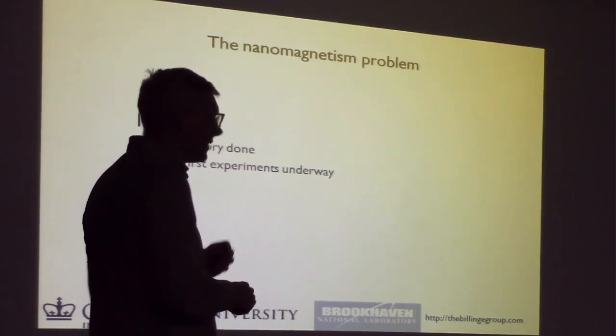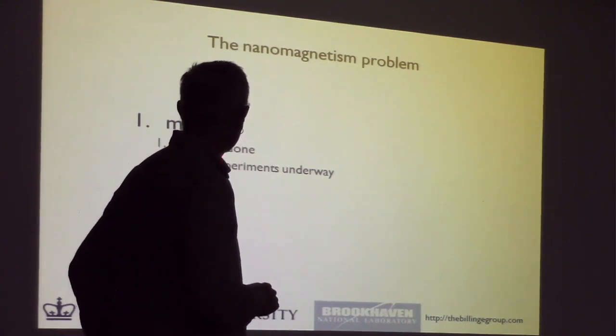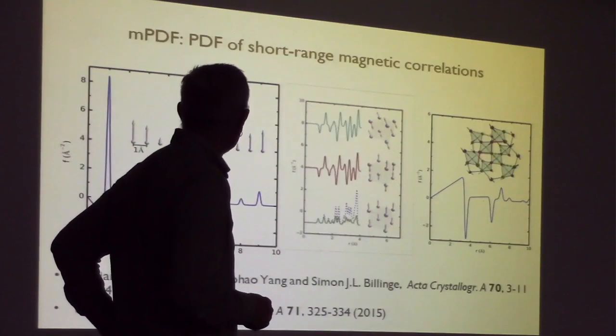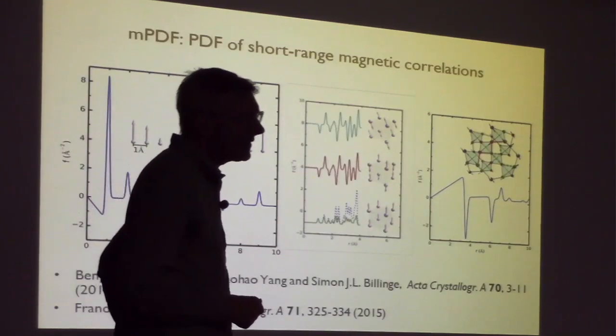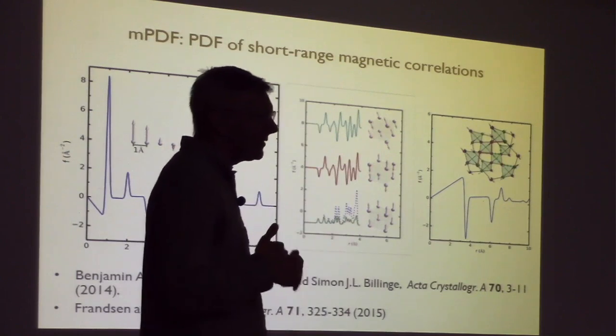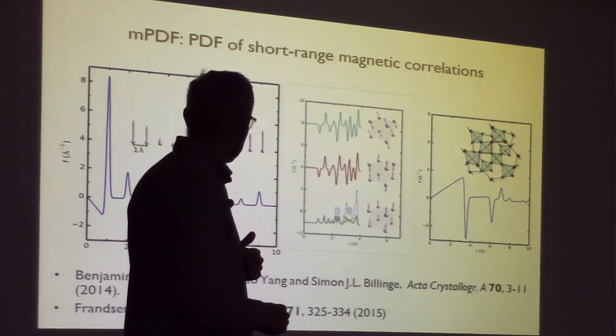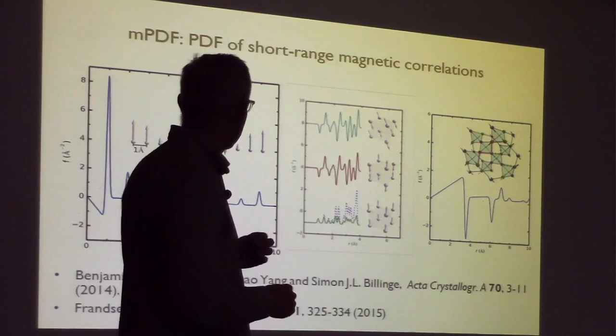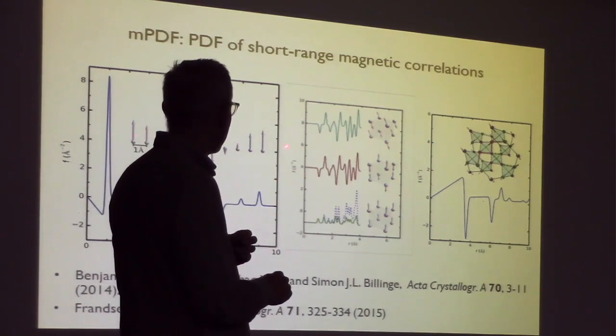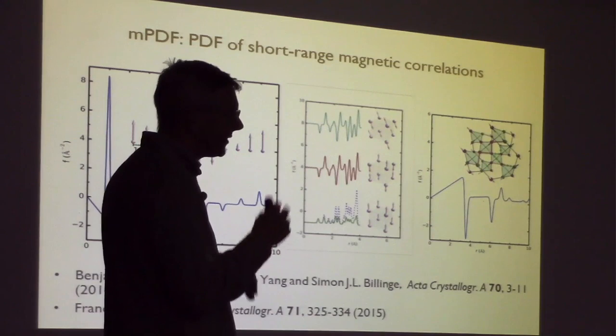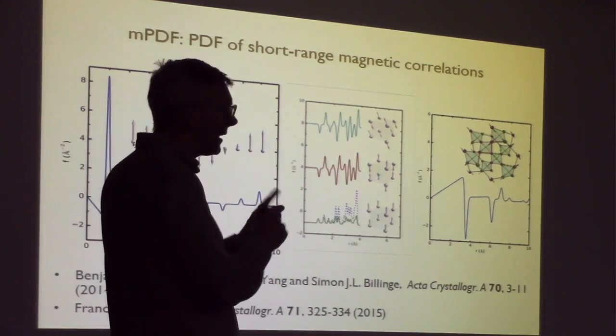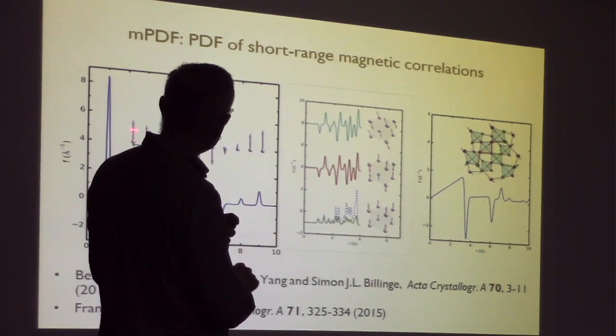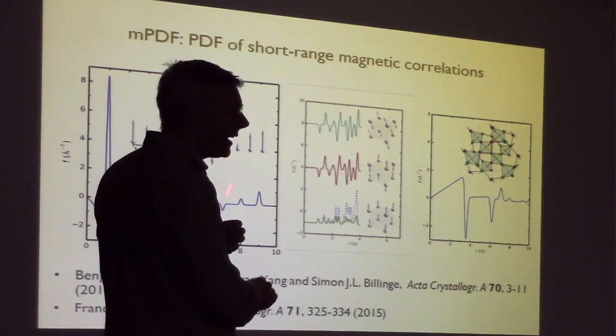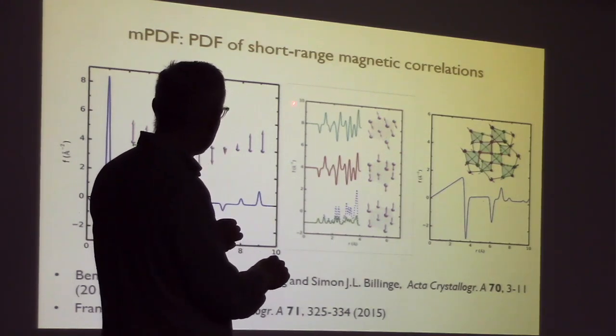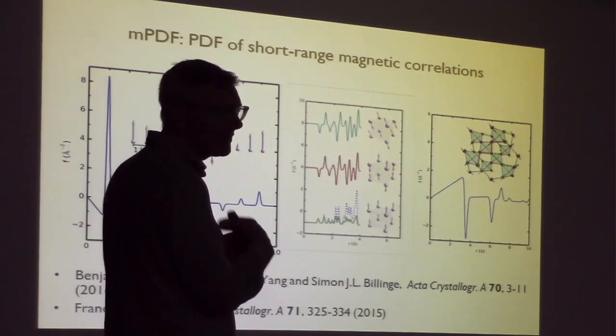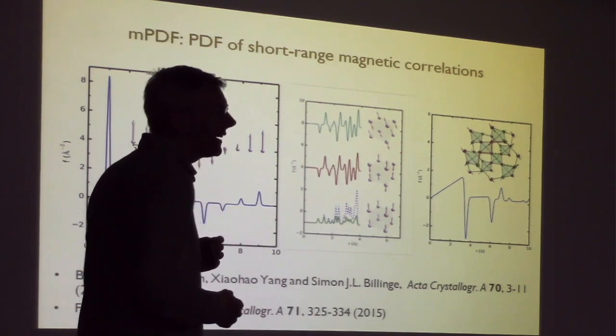And we actually just did this very recently with my graduate student Ben Frandsen, so MPDF, or magnetic PDF. And it turns out it's very interesting. So the theoretical development was to develop the equation for magnetic PDF. And then we can compute it, and you can look at different magnetic structures. So this magnetic structure is a spin chain. So basically, it's a made-up one. It's a one-dimensional thing where there's basically ferromagnetic correlations between neighbors, but there's this modulation that makes it go anti-ferromagnetic with some longer wavelength. So it's some beautiful spin chain.